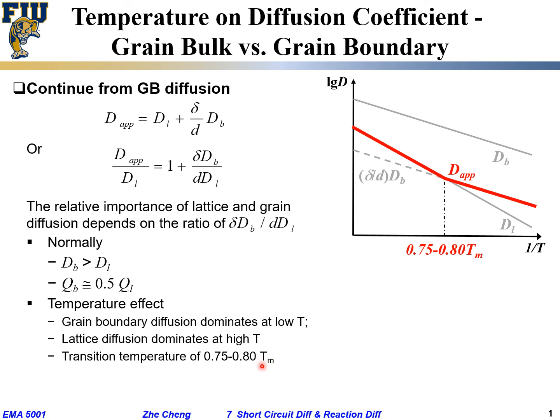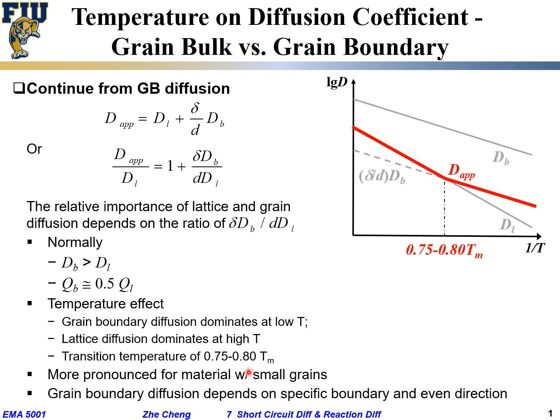The transition temperature is typically around three-quarters of the melting point — below that, diffusion is largely determined by grain boundary and defect contributions. This effect is more pronounced for materials with smaller grains, since smaller average grain size d means delta/d is larger while the grain boundary thickness delta remains roughly constant. Grain boundary diffusion also depends on the specific boundary type and sometimes even on direction.